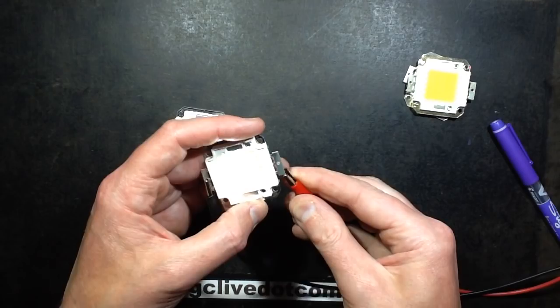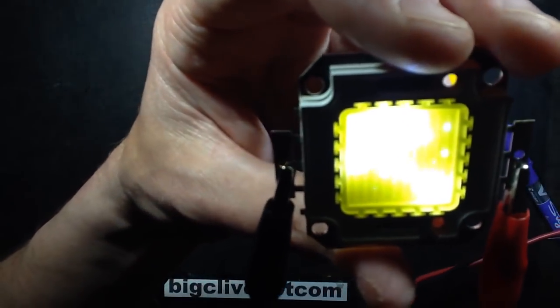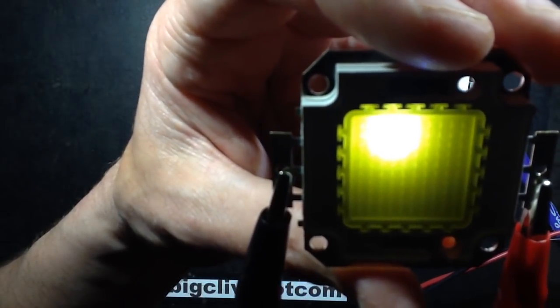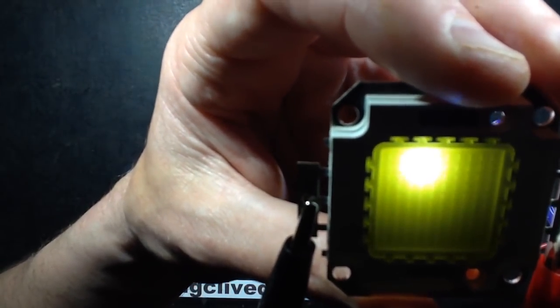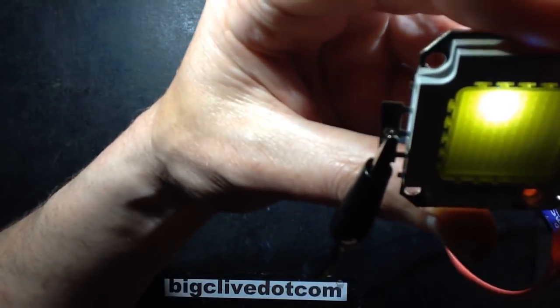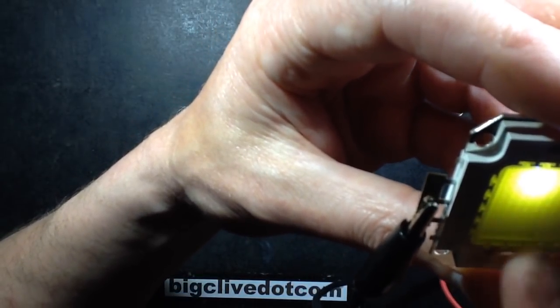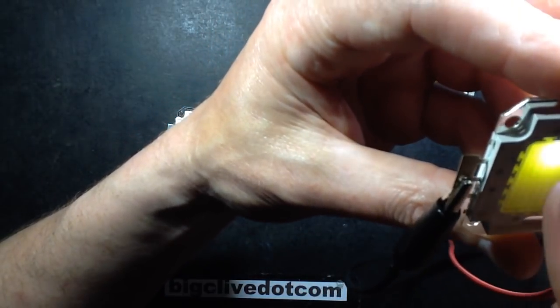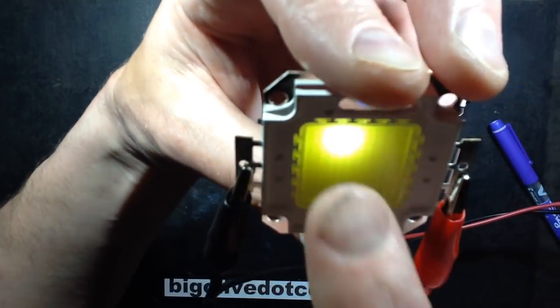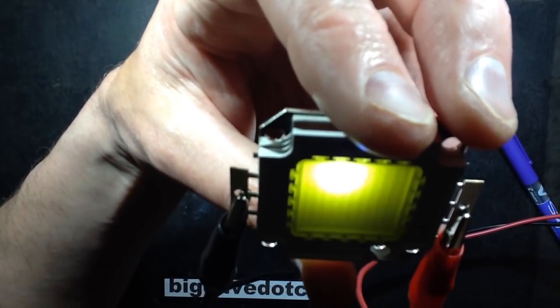So let's get another LED. And it's the exact same thing. It's a patchwork except it's really notable. If I turn it down a bit so you can see it, it's got one LED lit brightly. And you think so what's happening with the other LEDs? They're all passing that current. At the moment it's at 12 volts and it's showing 41 milliamps. So there's 41 milliamps passing through all these other LEDs in series of that one LED, and they're not emitting any light whatsoever. So they're, as far as I'm concerned, they're duff chips.